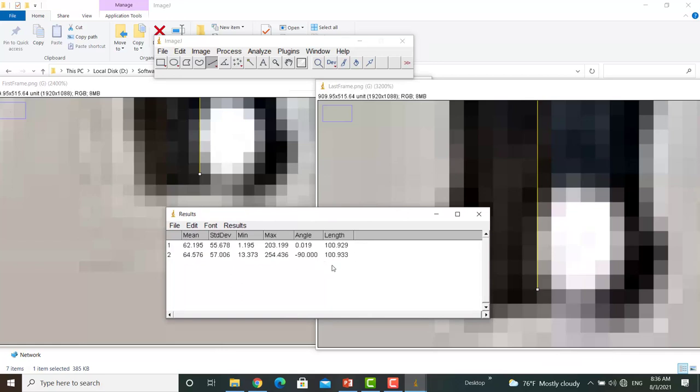Here is the length of the line in the last frame, and the strain in the y direction is also near 1%. We can calculate Poisson ratio from two strains, and surprisingly, the Poisson ratio is negative for this structure, which shows that this structure shows auxeticity and falls into the category of metamaterials.